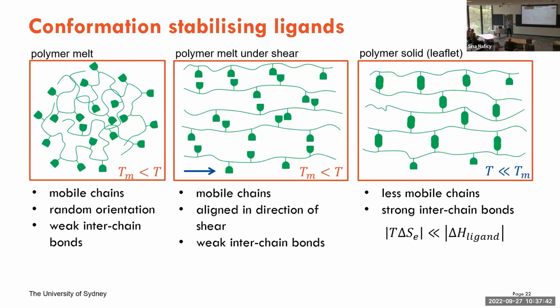One approach is by incorporating certain ligands into the backbone of the polymer. After they are oriented, these could interact with each other to form either permanent or very strong temporary bonds or crosslinks, which are strong enough to resist the tendency of chains that want to coil back at the temperature that they are being used.